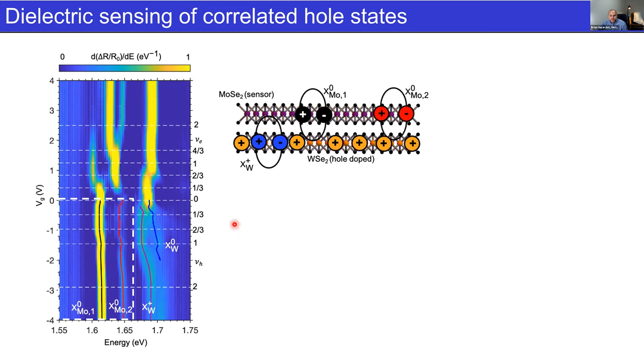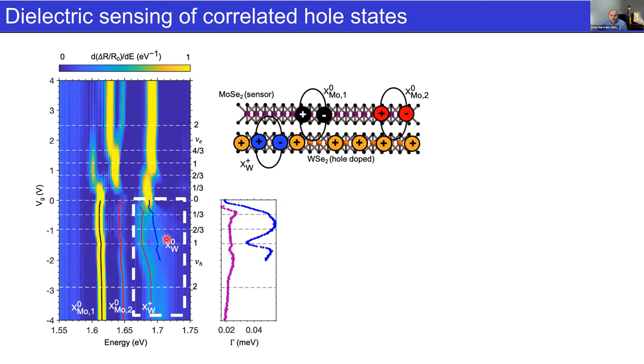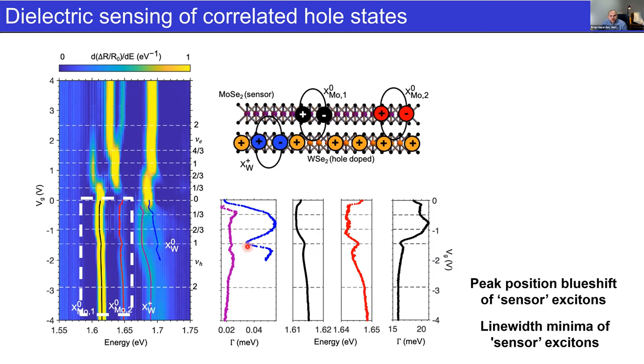So if we focus, sorry, these slides are maybe out of order. So what we see if we focus on these peaks here, is that we see a dramatic shift in energy of these Moiré excitons, so the red and the blue. Sorry, I can't even tell, is that black and blue, purple and blue? I'm going colorblind, I think. We see a dramatic shift in energy as we go towards these strongly correlated states. And as well, the line width dramatically changes as we go towards the filling of one hole per site, which you see here.